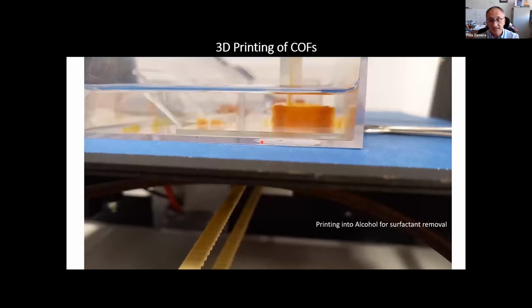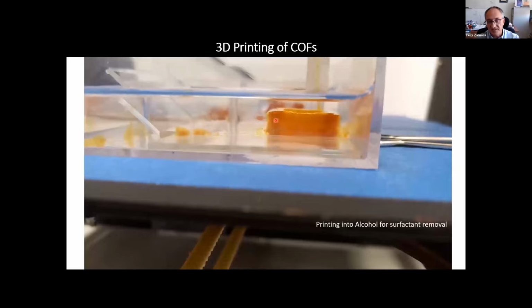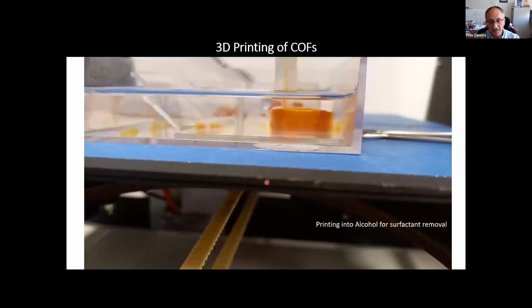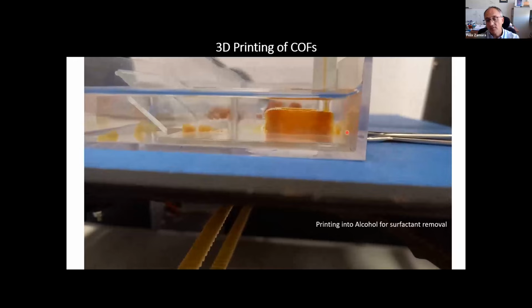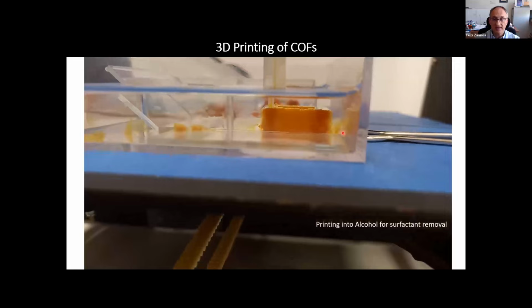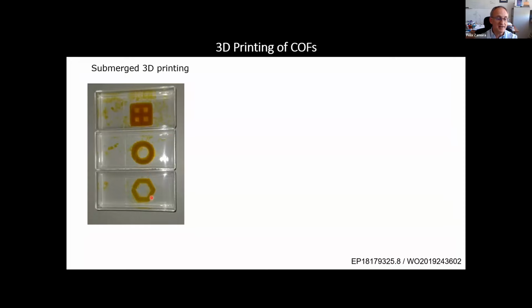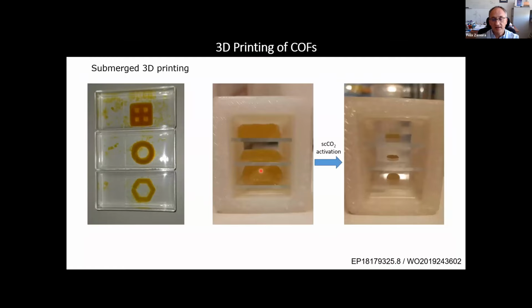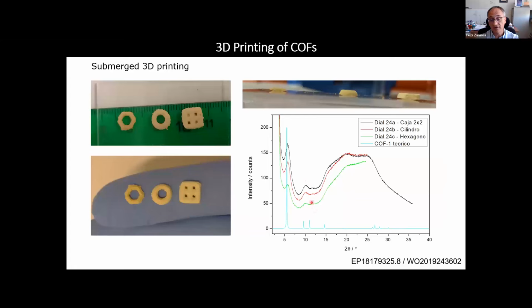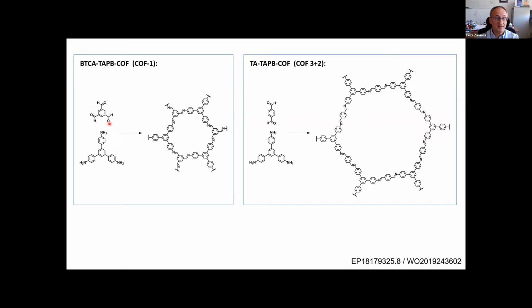And this is the experiment. Here you observe the tip moving and forming the 3D structure. You can also observe that we run the experiment in a pool containing alcohol, and the idea is that in that way we eliminate the surfactants that come with the initial nanoparticles. So at the end of the process, you have gels based on just the COF, without surfactant, and then you can eventually activate these structures and go from the gel to aerogels. And this is the final structure. They are chemically robust. They show crystallinity. They show porosity. And we have already run these experiments for these two structures.